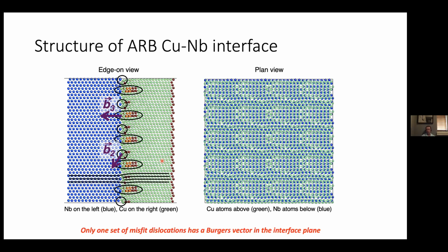Here's another set of dislocations that is present in this interface. This one also has a Burgers vector that points out of the interface plane. This one also is not going to glide easily in the interface. If you look top down, there's a third set of dislocations. And I'm sorry, I'm sort of telling you this information about the locations of the dislocations without proof, if you will.